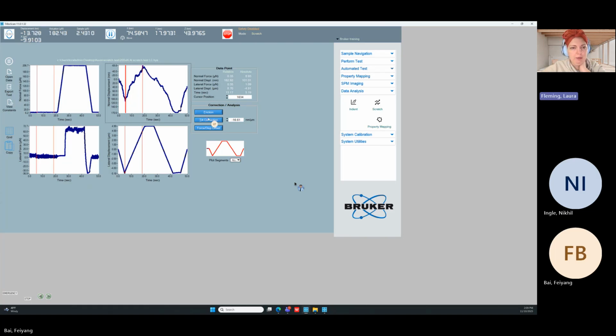cursors, and then only then can you hit tilt correction, because what that does is it takes the normal displacement between the 2 points and it says this should be 0, and it flattens it. So if you just hit tilt correction without choosing those points, you're changing the data strangely. It doesn't make sense. You have to pick where you measured the tilt. And we measured the tilt here because it has 0 normal force and we are scratching along the sample or tracing along the sample.